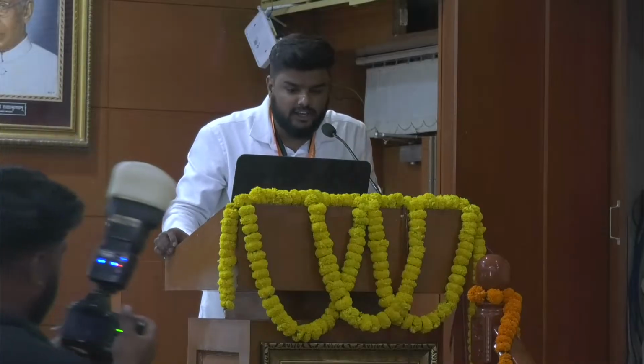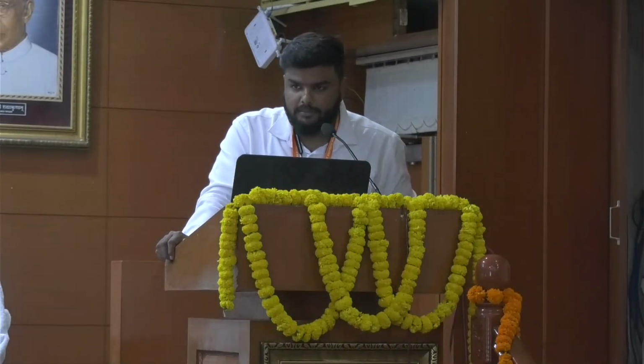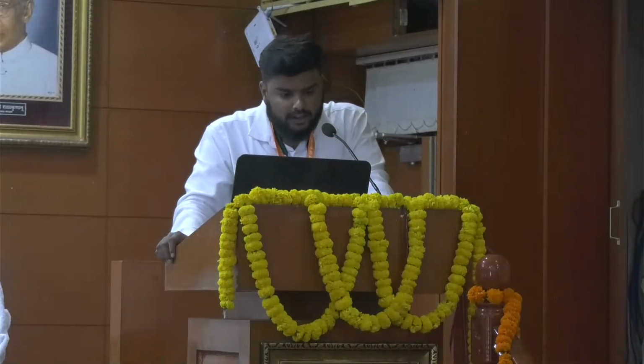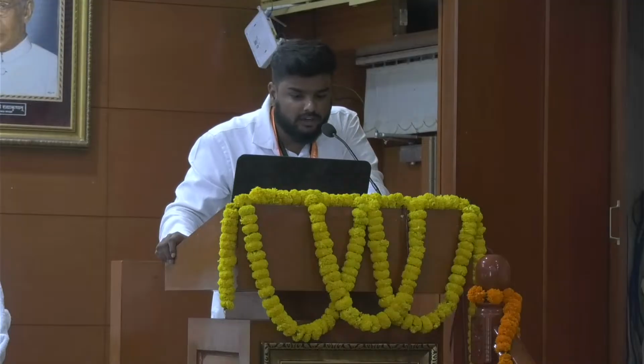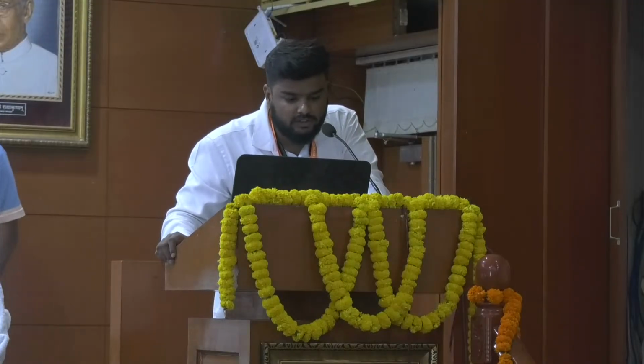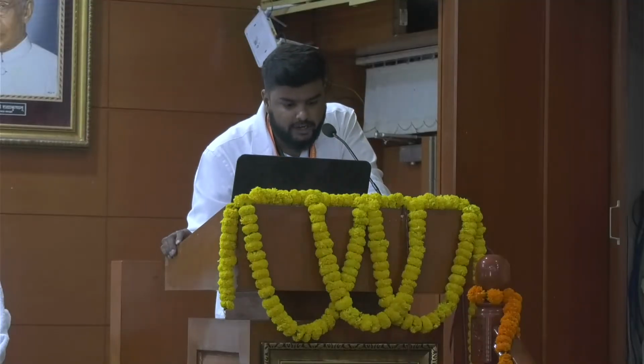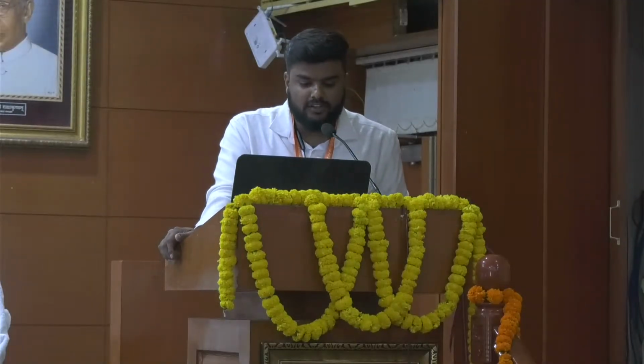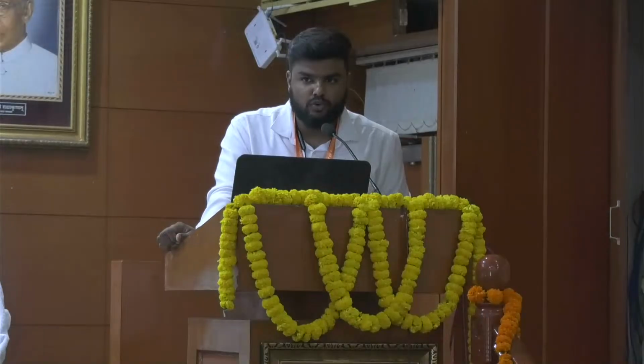And in this study, I have doped multiple rare earth metals, gadolinium, lanthanum, and holmium in the nickel ferrite to enhance its electrical and structural properties. Rare earth doping modifies the lattice, introducing strain and enhancing grain boundary effects, which I am going to talk about in the next slides. Grain boundaries in ferrites contribute to increased resistance and leakage current. Actually, in my application of ferrites, we have to increase the resistance for better applications.